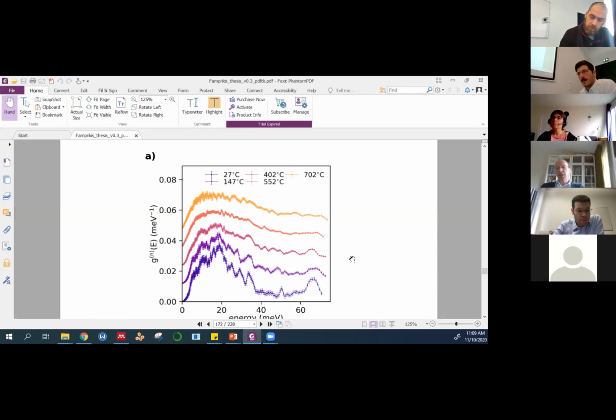So my question goes then, I should rephrase: how can you be sure that it is an overpotential? Obviously by changing the conductivity, and did you see people doing that, and what happened? Because you can do something super slowly. Yeah, exactly. But that's what people try, right? A typical example of that is the early cyclic voltammetry results that would tell you that LGPS is stable up to 10 volts or whatever. Exactly. But if you measure at an actually slow speed and take a few hours or days for the measurement, you will see very clearly the peak of decomposition.